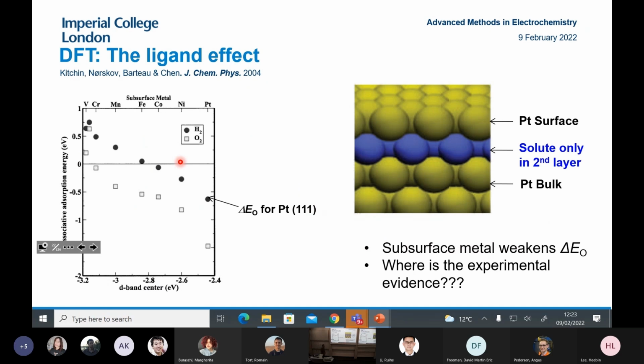So the way we decided to do that is using an effect known as the ligand effect. This was an effect that had been studied a lot in theoretical calculations. This is showing the oxygen binding energy for a number of different platinum surfaces, all with another metal in the second surface layer. So what you can see is that usually when you have a dissimilar metal, so this is platinum on top, if you put another metal in the second surface layer, you actually weaken the binding to both hydrogen and oxygen. This is called the ligand effect. A lot of people studied this in theory, but not in experiments.